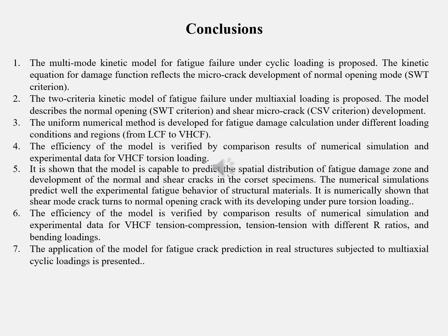And coming to the conclusion, we introduced a multi-mode kinetic model for fatigue failure prediction under multi-axial loading, and this model has good agreement with the experimental data, and it can predict the change in the crack propagation mechanism. For example, particularly here we show the results for a torsion crack that is initiated under shear conditions and afterwards propagates under normal crack opening conditions.